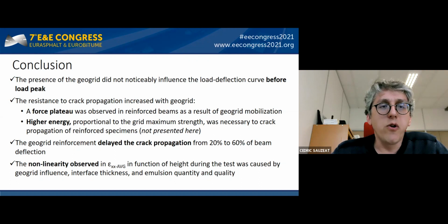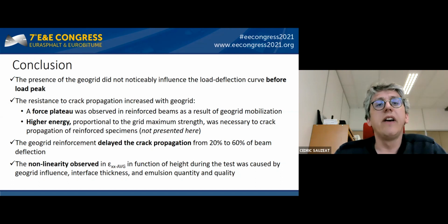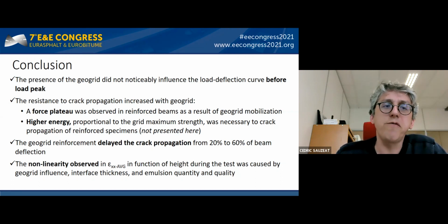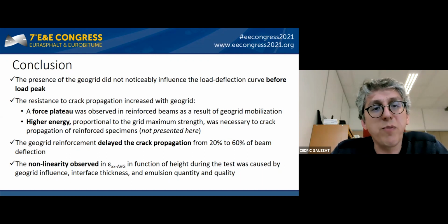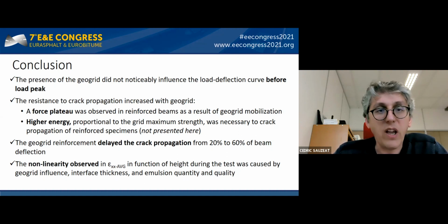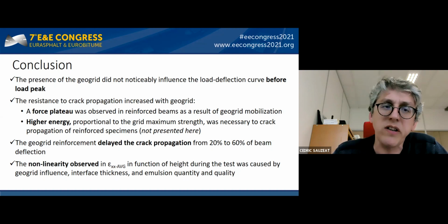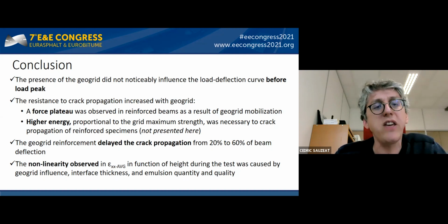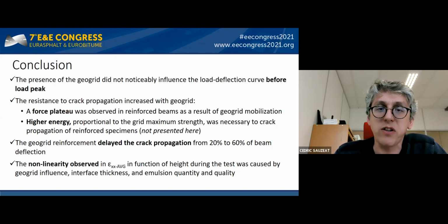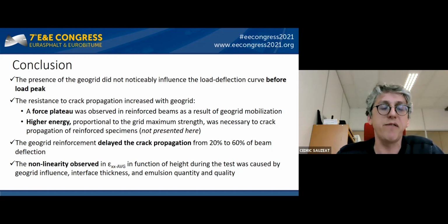So the conclusion: the presence of the geogrid didn't noticeably influence the load deflection curve before the load peak. The geogrid only affects the crack propagation after the peak. A force plateau was observed in the reinforced beam as a result of the geogrid mobilization. And I didn't show you here, but a higher energy proportional to the grid maximum strength is necessary for crack propagation of the reinforced specimen. The geogrid reinforcement delayed the crack propagation from 20% to 60% of beam deflection.